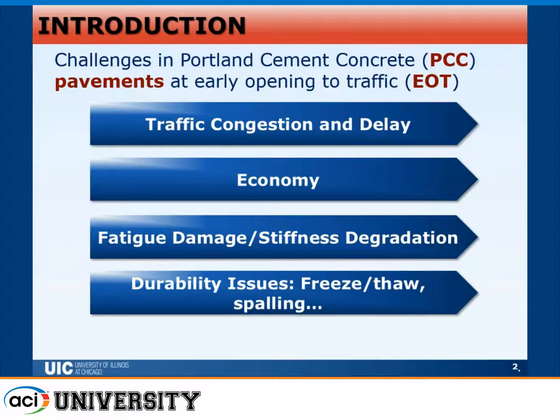And most of the design parameters that are taken into consideration in the design of the pavements are mainly also hardened properties. However, we still do not take into consideration the effect of the stiffness degradation at very early opening to traffic, very early age. And when we say very early age, we're talking about 12 hours, 1 day, 2 days, and 3 days. The current specification is mainly focused on strength, as I mentioned.